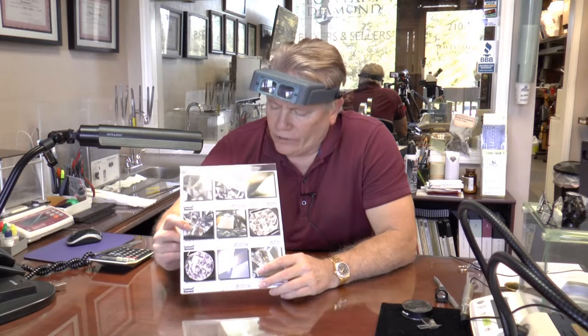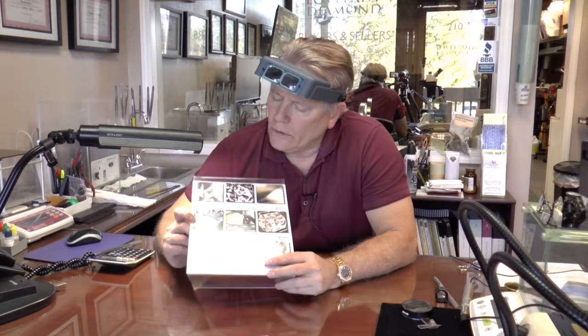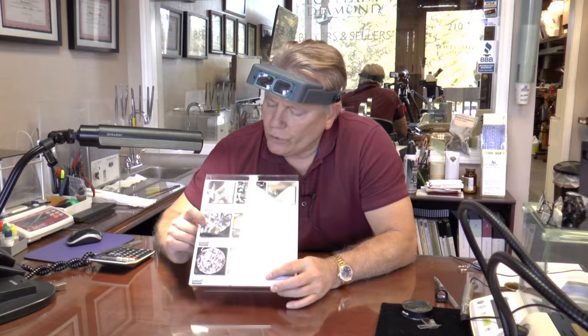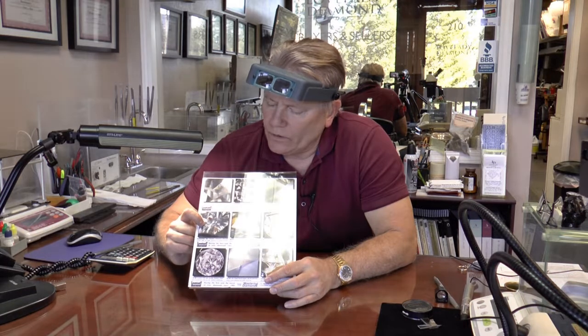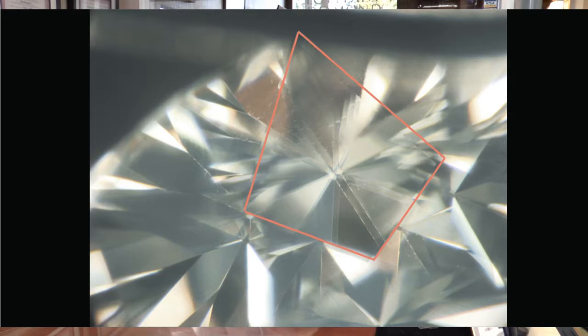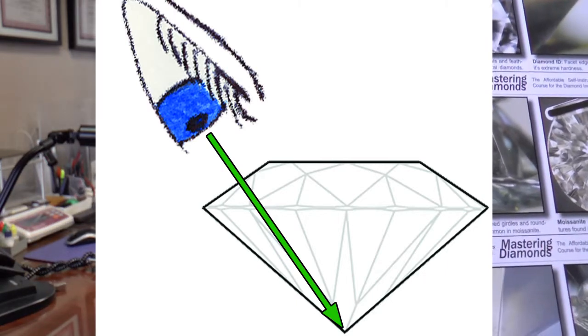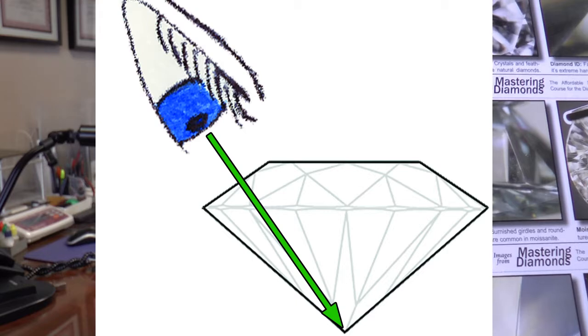One of the biggest convincing imitations or simulants today would be the moissanite. Natural moissanite was discovered by Dr. Henry Moissan. The main factor with these is that they are doubly refractive. So by looking through the main kite-shaped facet to the culet, which is the bottom point, you'll be able to see a doubling of the culet. This is going to be quite apparent on larger stones. On the smaller stones, you're going to have to be a little bit more careful about identifying that.